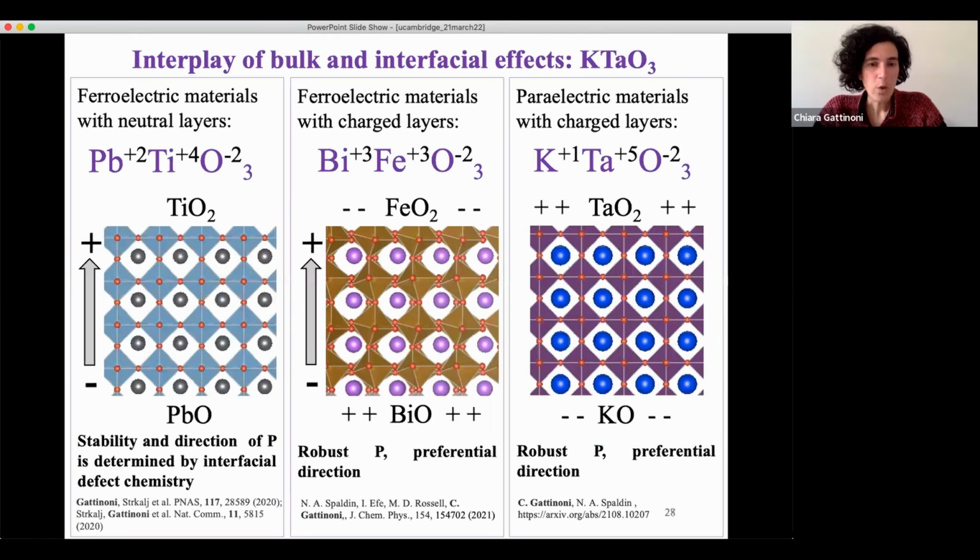So what we found then is that the electrostatics of the system really influence how the system responds to the ferroelectric polarization, or how the ferroelectric polarization responds to being in the ultra thin level, and whether the system has charge layers or not is really, really important. So now we know how the systems behave. The big question next is understanding how we can make them switch easily.